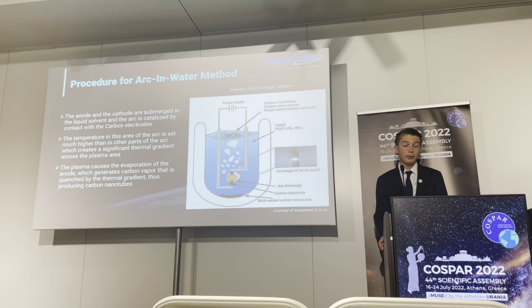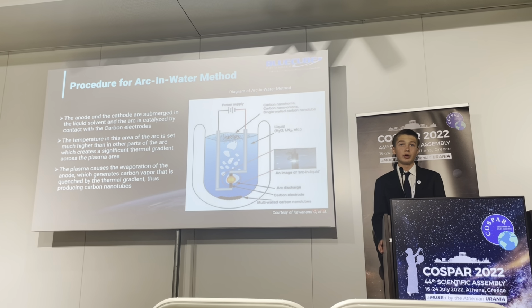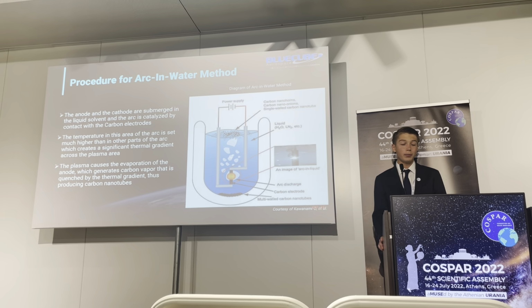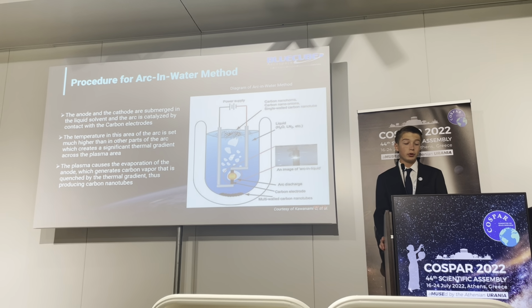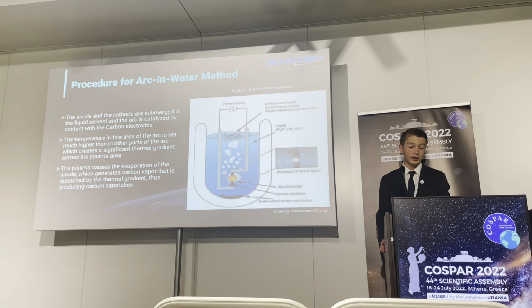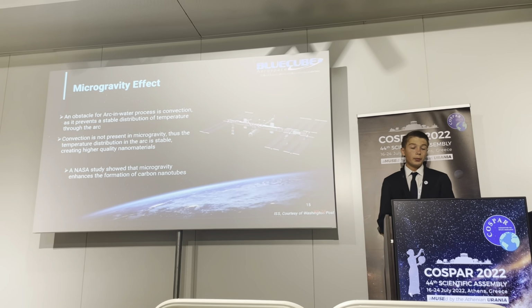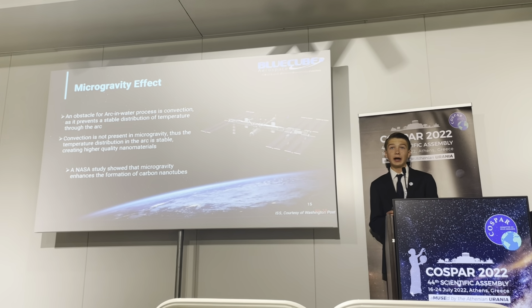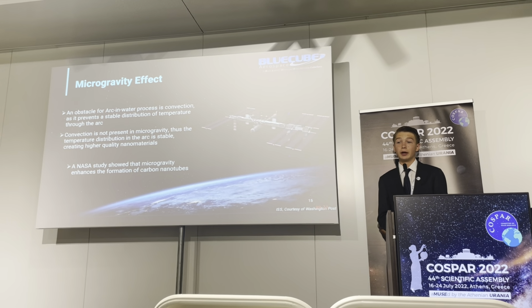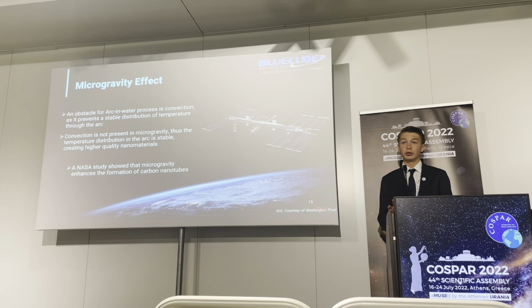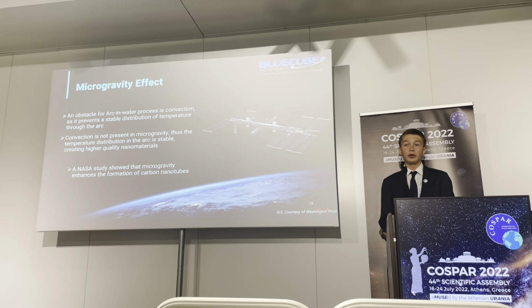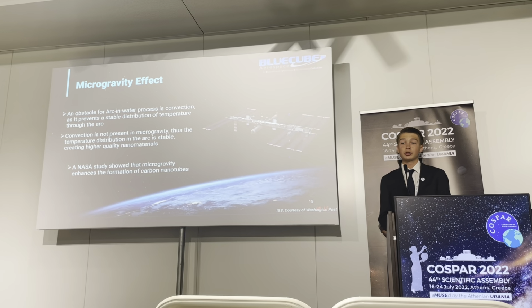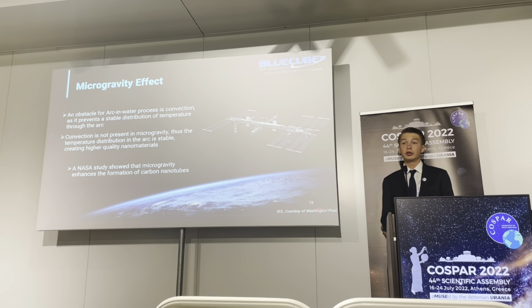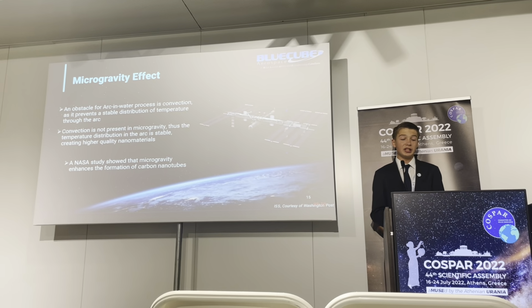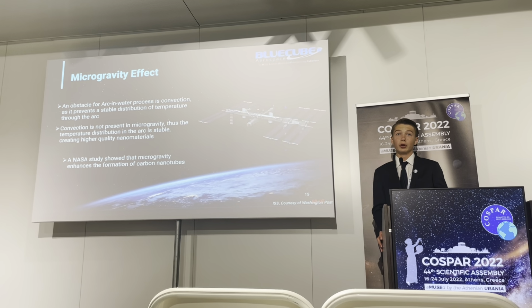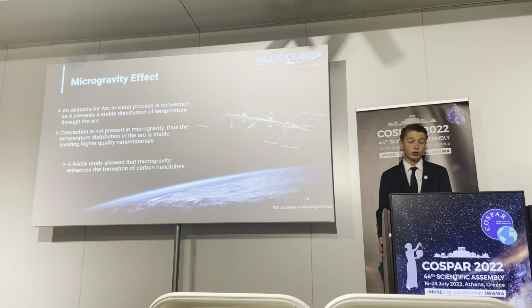This plasma then causes the evaporation of the anode, which generates carbon vapor that is quenched by the thermal gradient, thus producing carbon nanotubes and other related nanomaterials. The primary part of this process that is affected by gravity is creating a stable thermal temperature distribution across the water in the arc. Due to convection, it is much harder to create this thermal gradient and to keep it stable, which generally leads to the creation of less pure carbon nanomaterials and graphene.